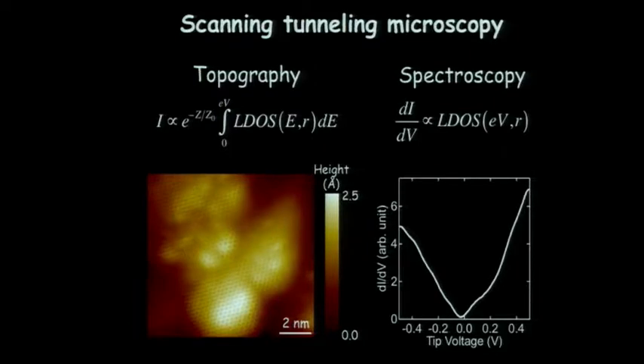In a topographic mode, we have our fixed sample, we bring our tip very close, and the tunnel current you get is exponentially sensitive to the tip-sample separation. That's the term out in front here. Any changes in the tip height give an exponential change in the current. Using a feedback circuit, we just keep the tip current fixed as we scan the sample, and so the tip adjusts to the surface profile. Using that feedback, we get a map of the topography. This allows us to see where the atoms are sitting on the sample and learn something about the morphology of the sample.